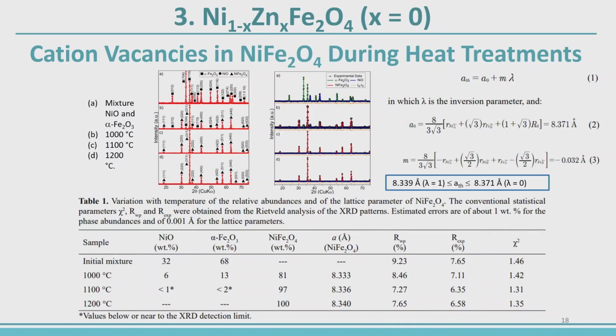It's just by checking the ordering, that there is a redistribution of the cations in the two sites, the tetrahedral and octahedral sites. But we notice that this theoretical formula cannot explain these results, because with lambda equal to 1, we have a lattice parameter that is close to the one for the 1200 sample, but the other one is not in this range, it is outside. So we need another explanation, and we propose that this is due to cation vacancies on the octahedral sites at low temperatures that are gradually filled up with cations as the temperature is increased.